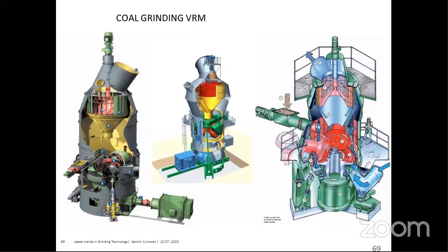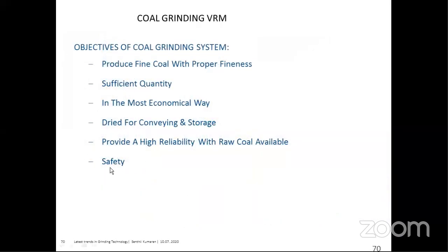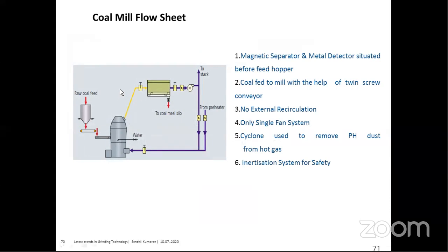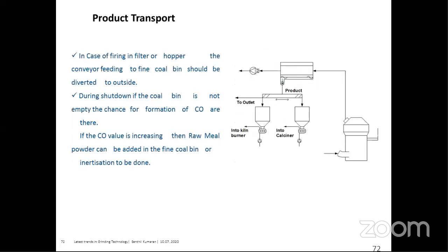So the basic difference between the coal grinding VRM and the raw grinding VRM is that the safety precautions are much greater in the coal grinding system. We have to ensure the safety of the system as well, and that is more important. For safety, we monitor temperature and CO levels more closely, we regulate the system with inert dust materials, and we follow more precautions in the grinding system. There is no external recirculation, and only a single fan. So this is the basic difference between the raw mill and the coal mill. So these are the vertical mills. Due to the time constraint, I'll move on.